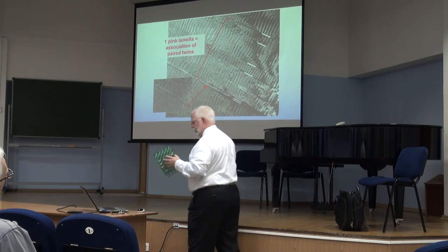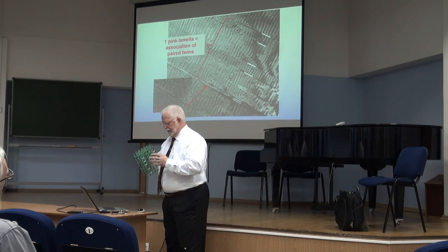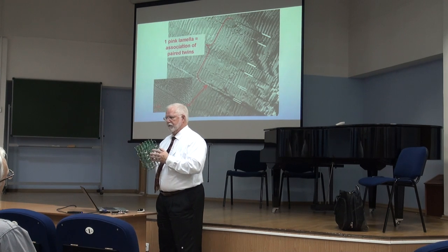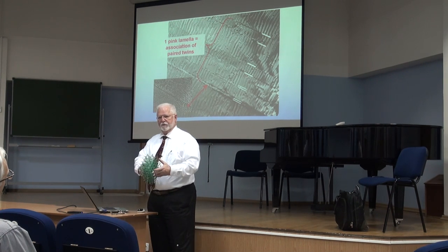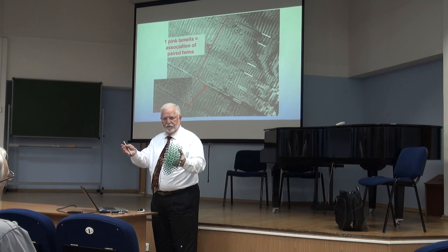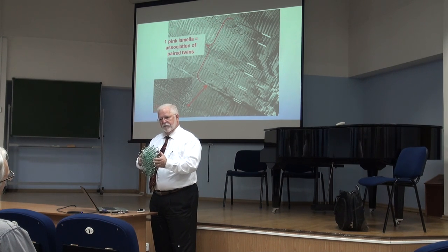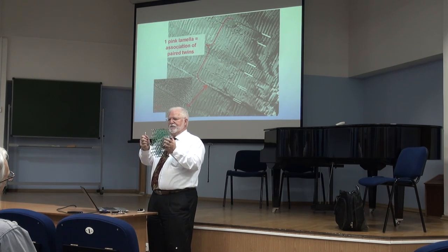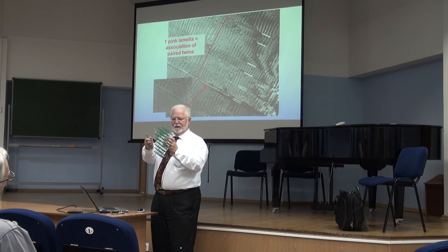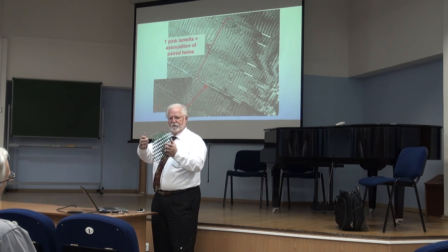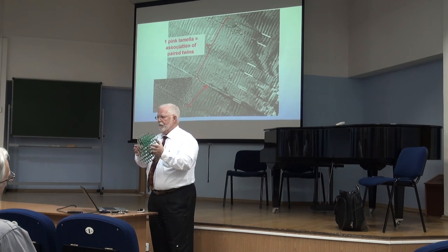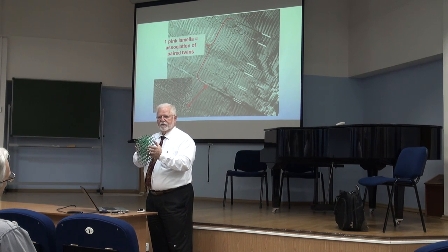Now, this is actually very understandable. What's probably happened to these diamonds is that when they were deep in the core of the Earth, there's very high pressure, it's stabilizing pressure, and there's actually fluid motion there. So they encountered something that plastically deformed. It took the diamond crystal and just tore it, okay? And made probably small regions or planes in the diamond amorphous, not crystalline.